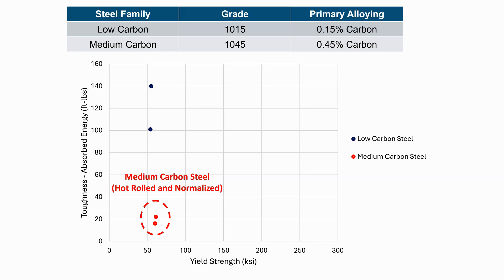As we compare the hot rolled and normalized condition of this 1045, you can see we have much, much lower toughness. This is about as low a toughness as you probably want to go. Generally, between 13, 15, or 20 foot-pounds absorbed energy is about as low as you want in most applications. If we were to take that 1045 steel, heat it to red-hot temperatures and water quench it without tempering, that steel might appear to have very high strength, but it's actually quite brittle — it absorbed a meager 3 foot-pounds before it fractured. We don't want high-strength steel that's very brittle because a notch and an impact could cause our component to shatter, which is not very safe. We generally avoid as-quenched, un-tempered steel because of that.